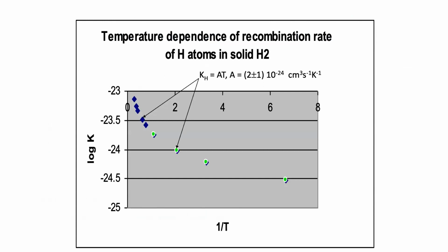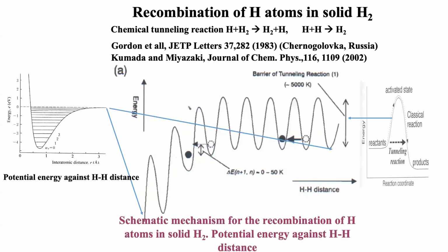On this curve, we show the logarithm of the rate constant versus 1 over T. If the dependence is proportional to T, we place all the results from other groups, and also the green point where we decided to check this dependence at low temperature. We did this because if you consider this tunneling, you can expect that at low temperature the rate constant will be slower.